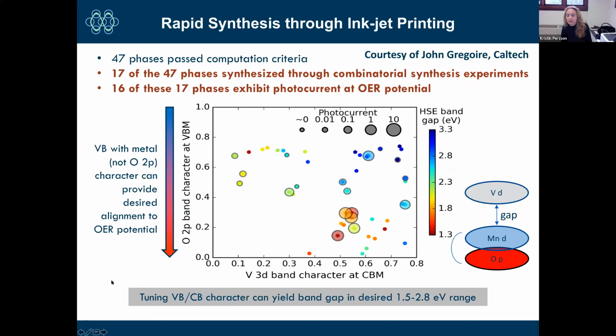And these were the results. And this is the cool stuff again, when you don't have just one phase. We gave 47 polymorphs that passed the computational criteria. 17 of them he was able to synthesize, which is quite remarkable in a fairly short amount of time. And 16 of those 17 exhibited a photocurrent.